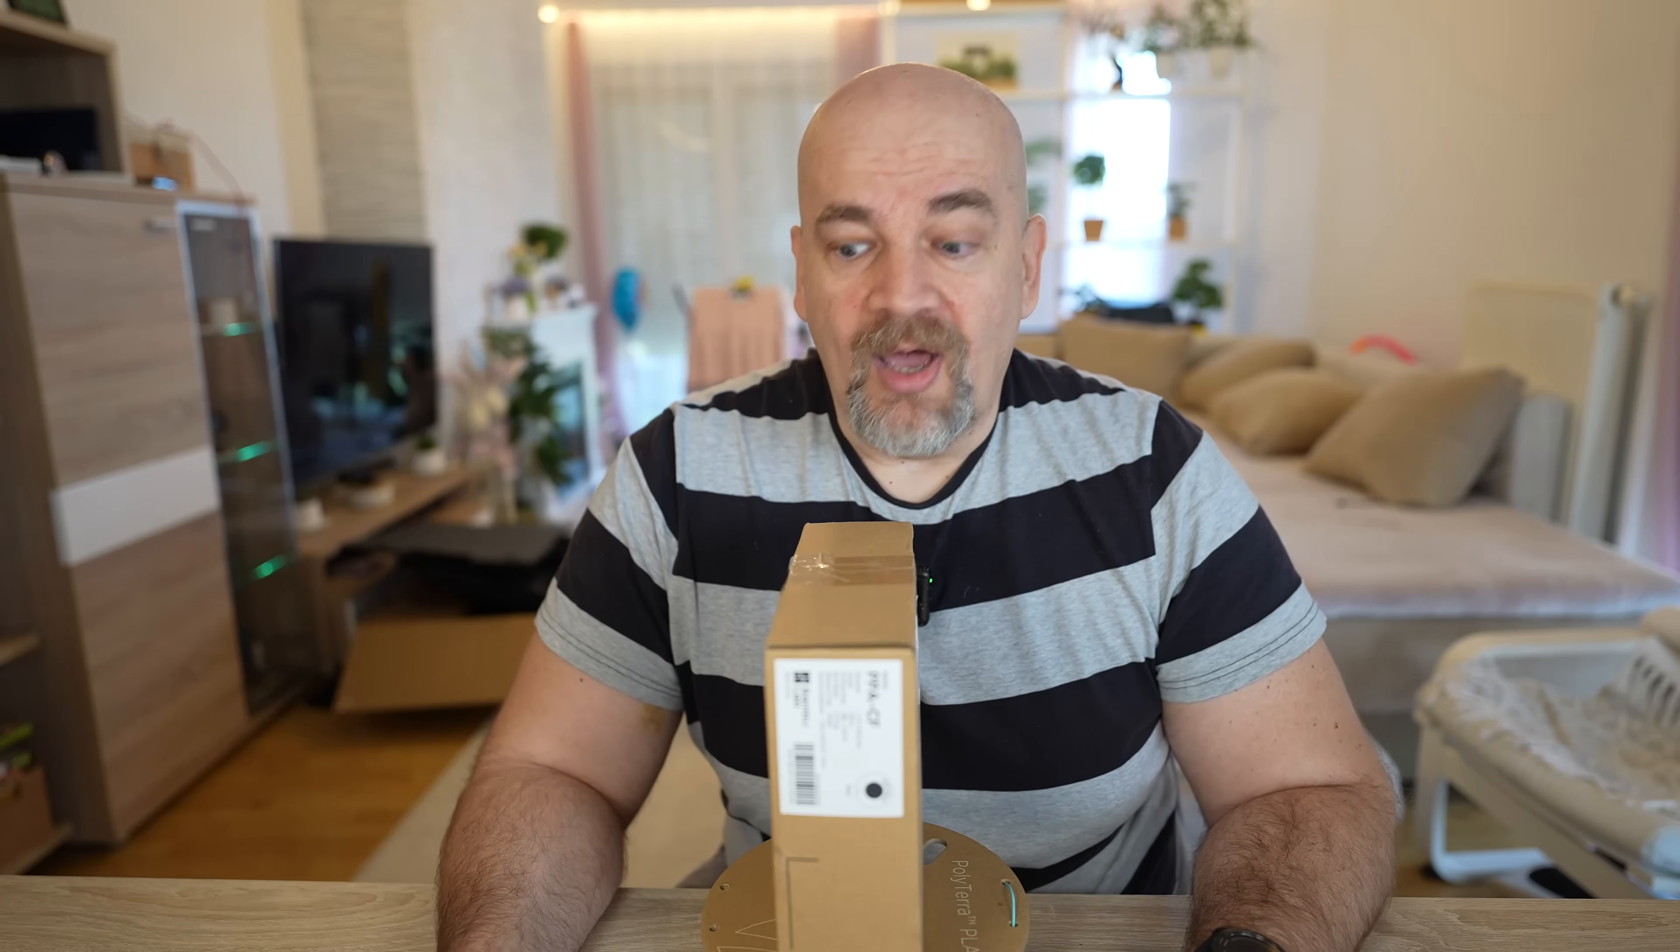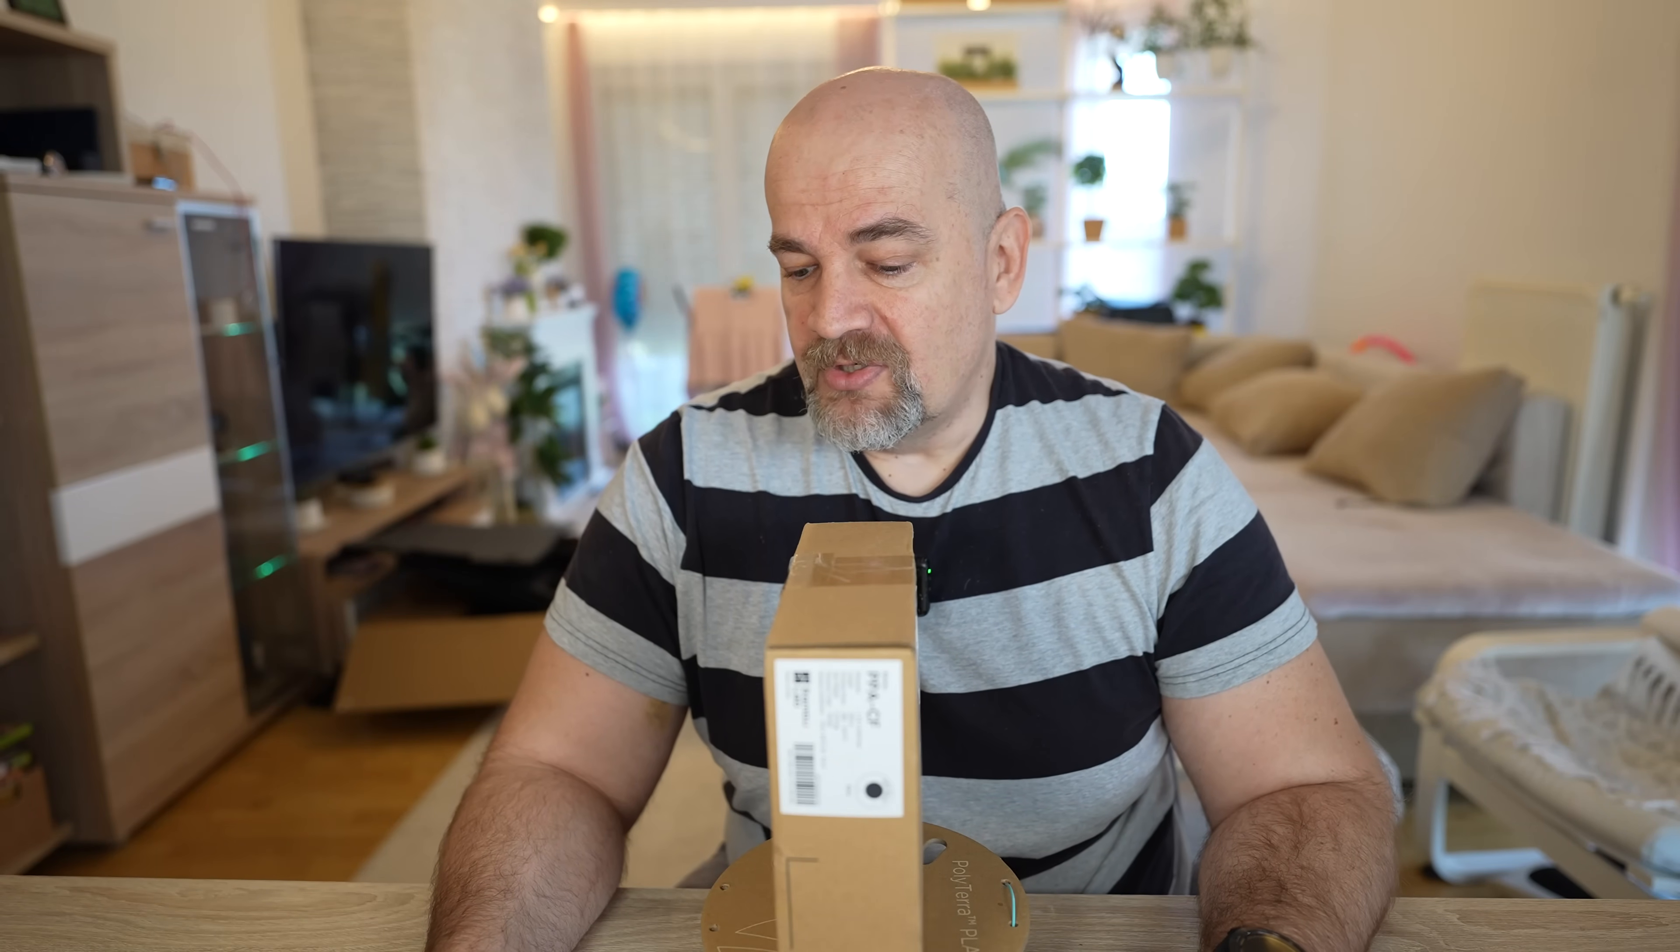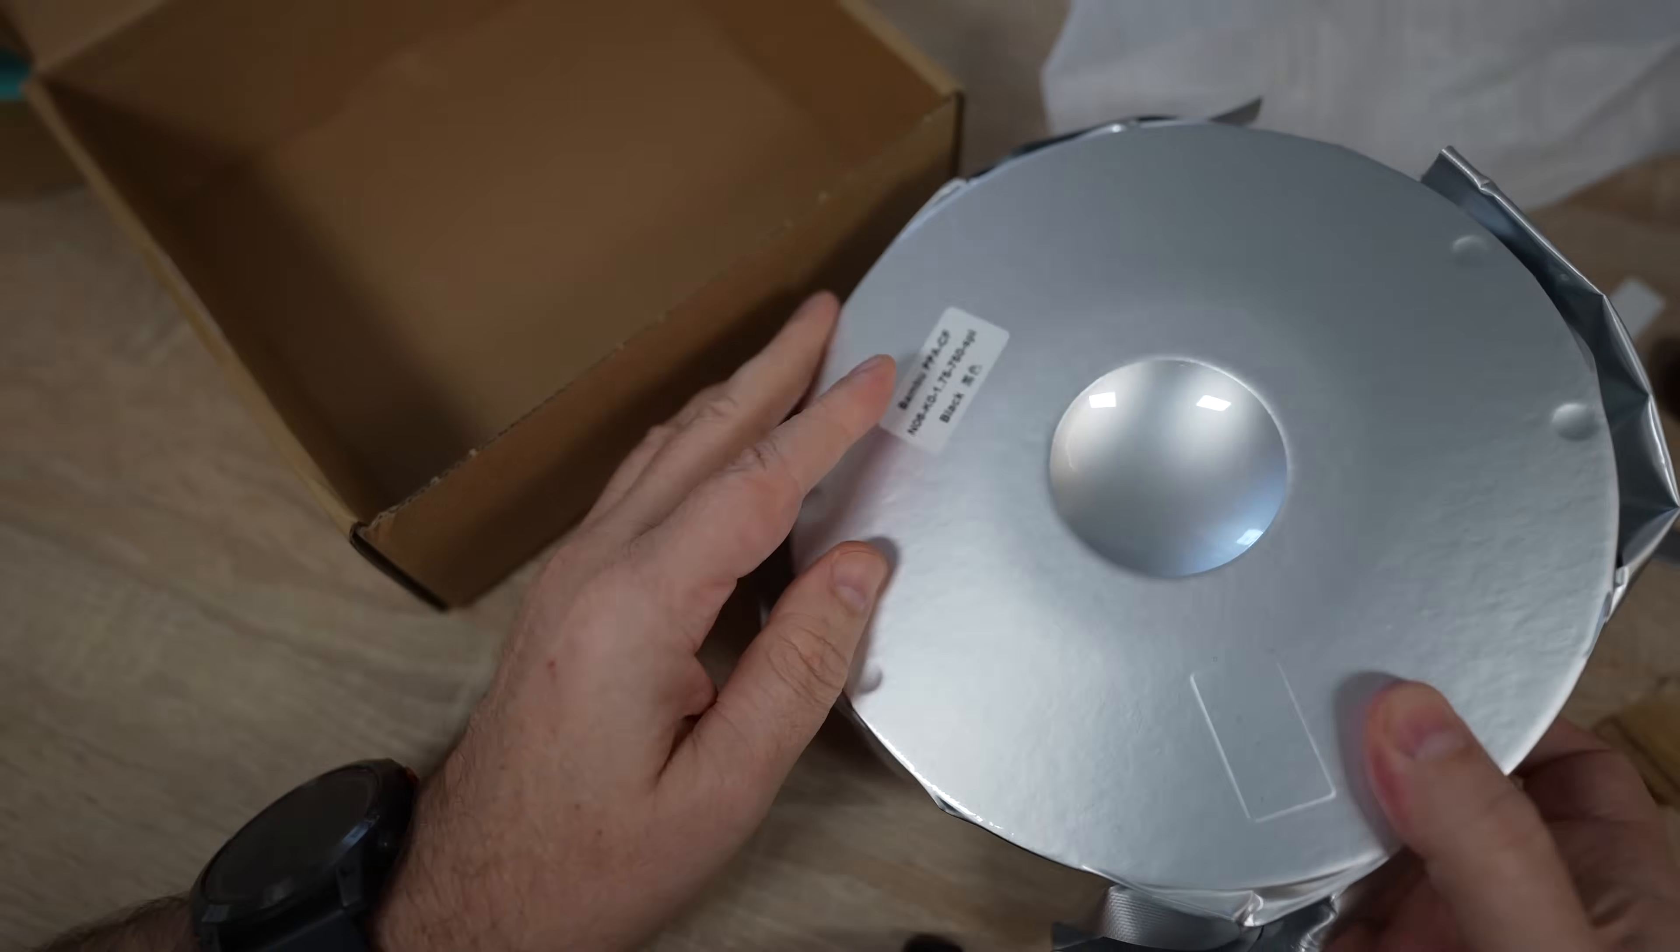It must be dried 100 to 140 degrees Celsius between 8 to 12 hours. Now this is too much. I will dry it maybe 2 or 3 hours, but the printing will be from the filament dryer too. The print temperature is between 280 and 310 degrees Celsius, and the bed temperature between 100 and 120 degrees Celsius. I will use the engineering plate with some glue stick on it.